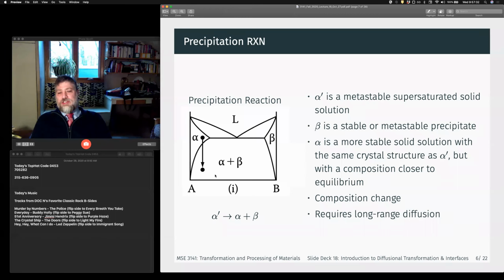and then quench down to some temperature here. So now if I quench down and I rapidly change my temperature, I now have metastable alpha, right? That's going to decompose to this composition and this composition, right? And it's important to realize that we're going to get a very different microstructure if we cool slowly versus if we quench down quickly. Right?